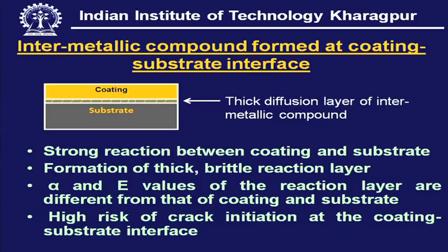So, under this condition of formation of a thick diffusion layer, there is high risk of crack initiation at the coating substrate interface during the actual loading of this coated product, or during cooling down of this sample or specimen from the reaction temperature down to room temperature.